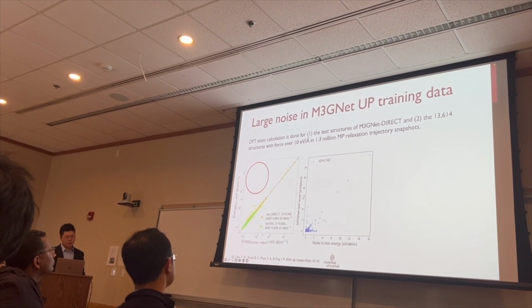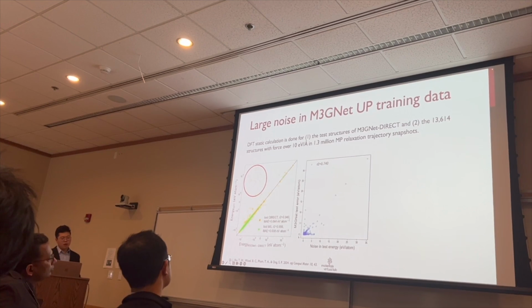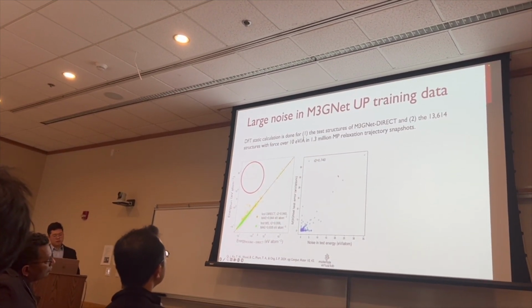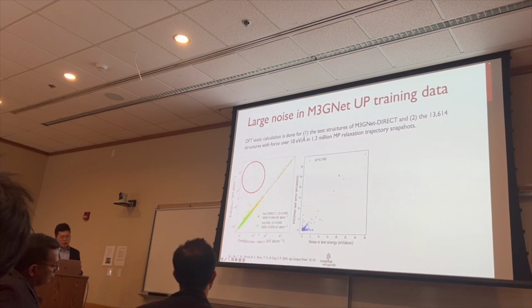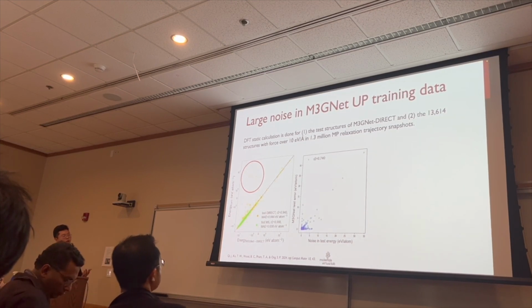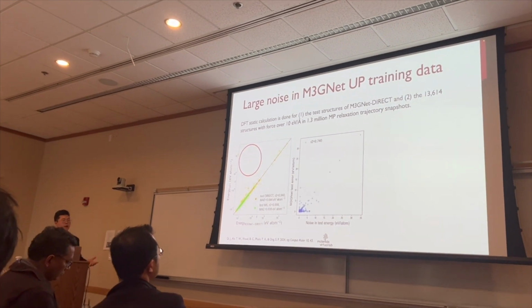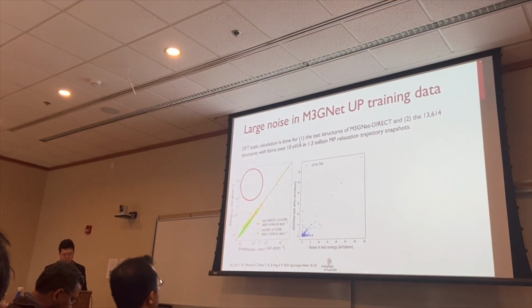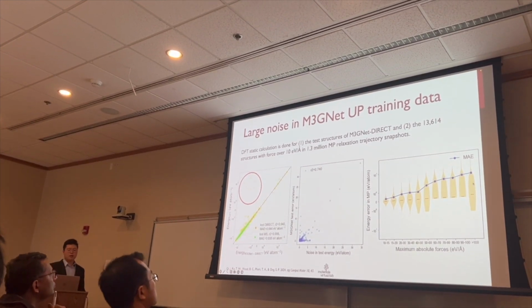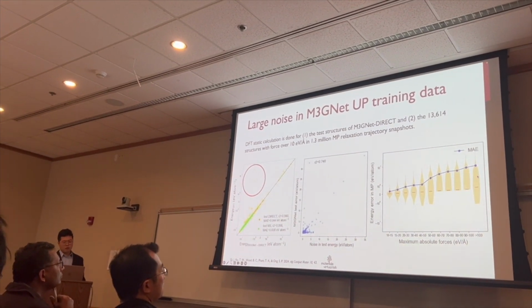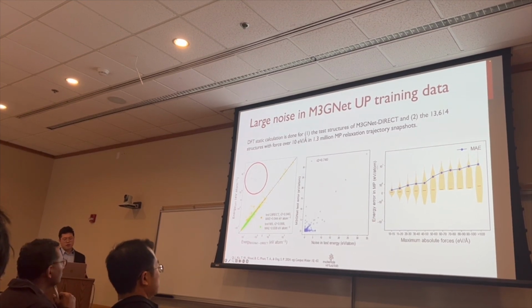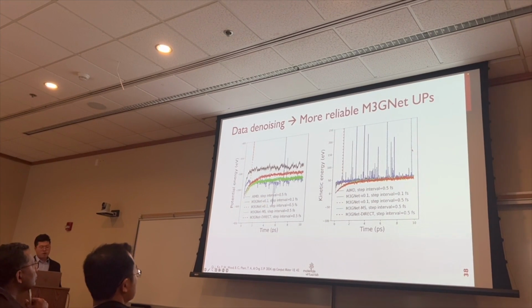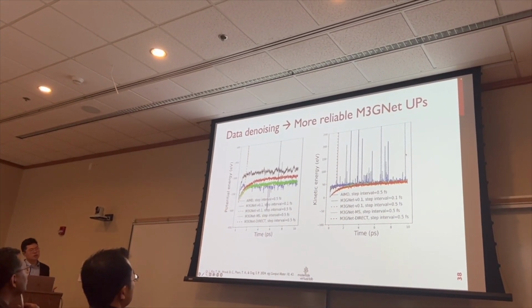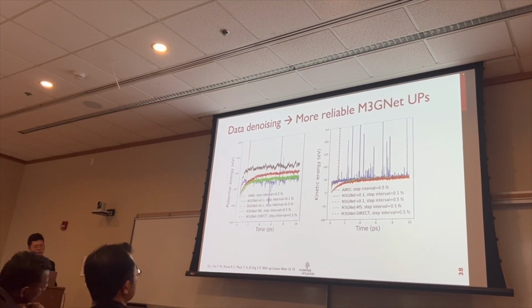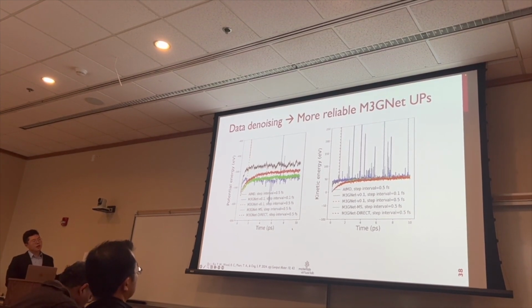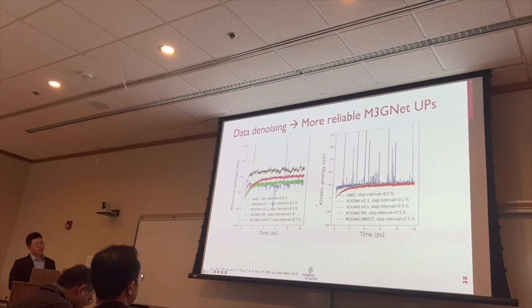Energy here, and on the y-axis is the M3GNet test error. So there is a large correlation between the M3GNet test error and the noise in the test set. This tells us that if we improve the training data and test data with reduction of noise, then we will likely result in an M3GNet with improved accuracy. So we indeed perform some static calculations for the structures with large forces. And we, again, confirm there is a noise in this energy in the Materials Project data. And by replacing those large force structures data with our newly calculated data, we find that both the manual sample dataset and direct sample dataset can result in an M3GNet that has improved simulation reliability.